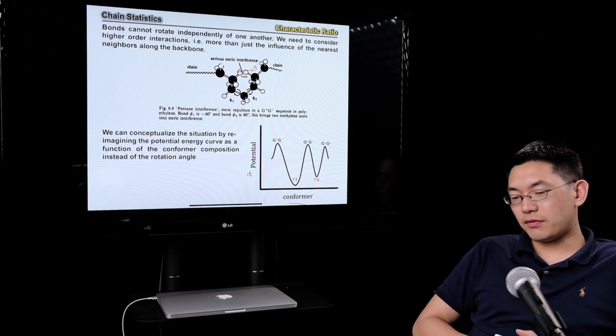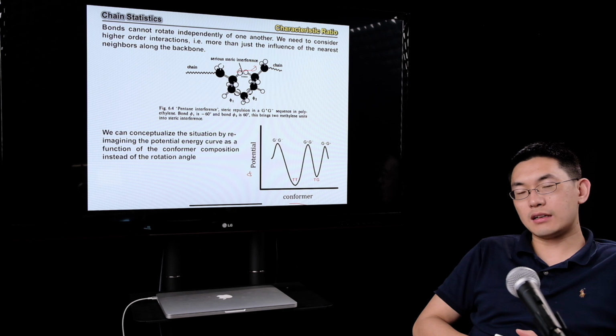Due to the self-avoiding walk, we will see that our chain also expands. The degree of expansion for a polymer in a good solvent does not depend on N to the power of 0.5 times L, but instead on N to the power of close to 0.6 times L. This power of 0.6 is an expansion factor, and we will discuss more when we talk about polymers in different qualities of solvents.